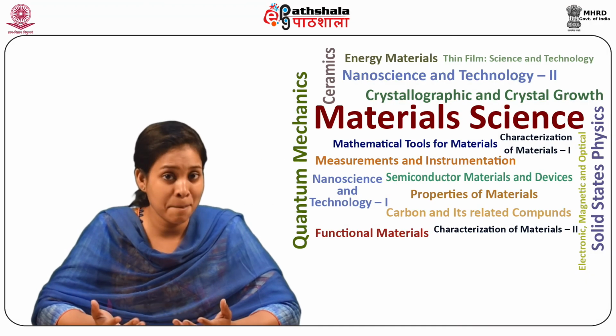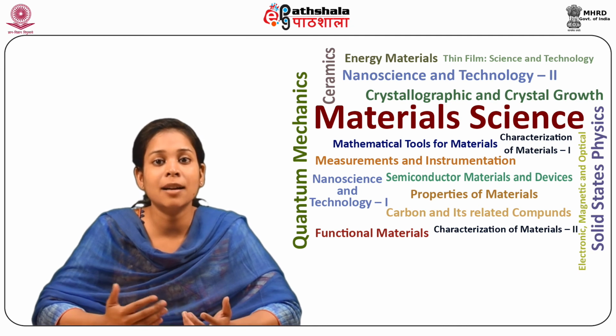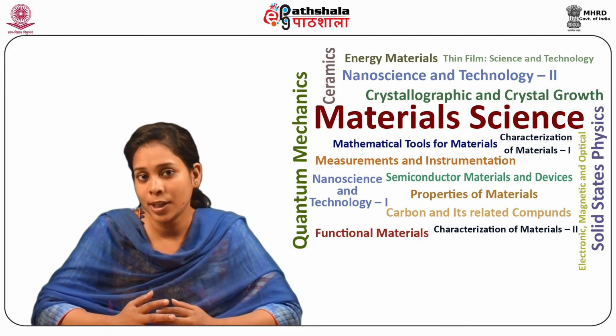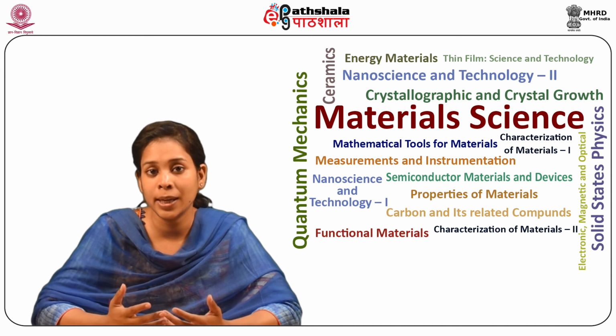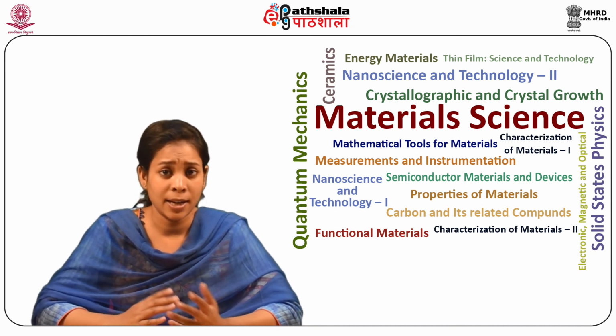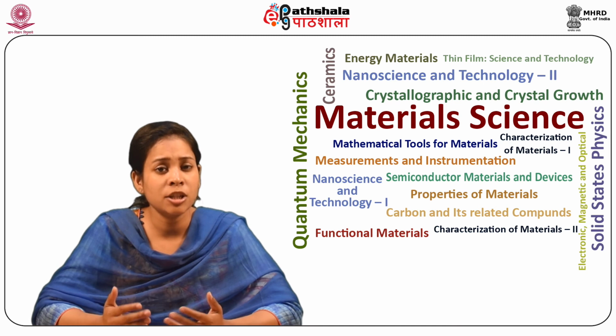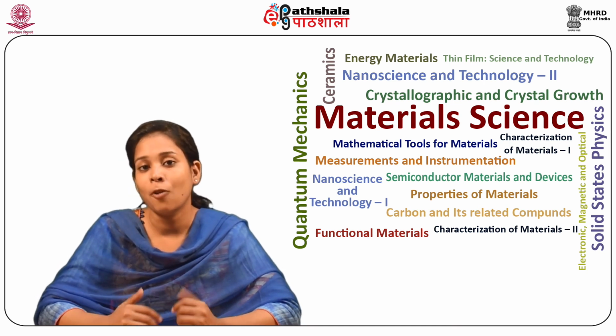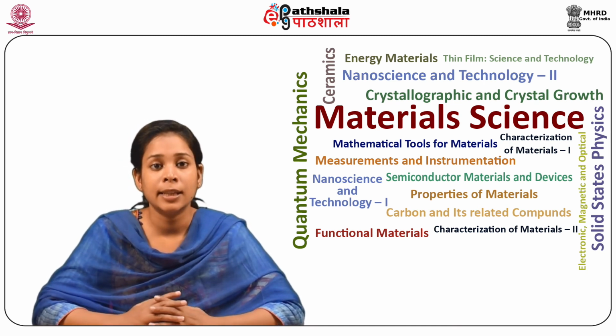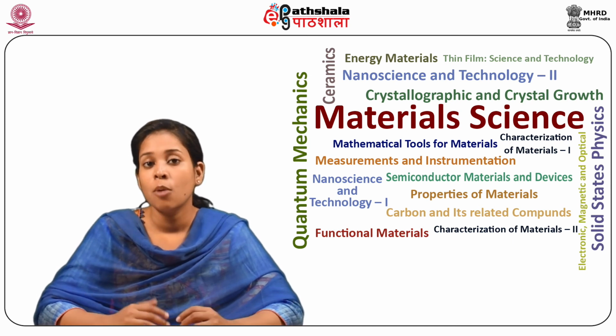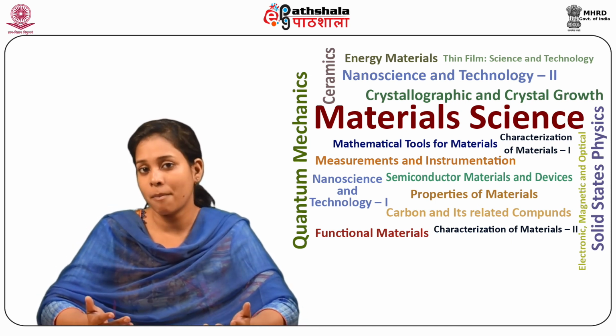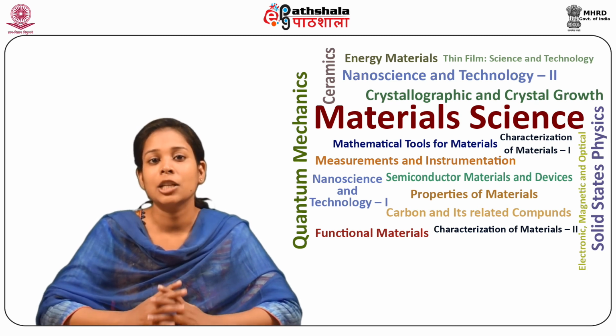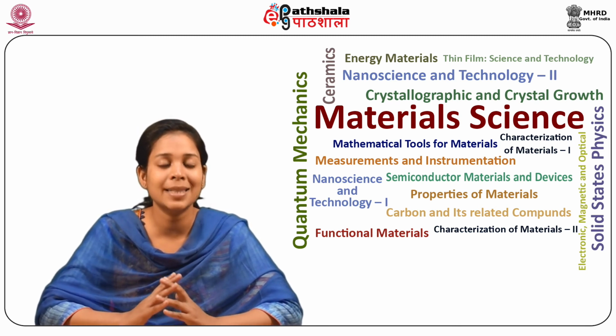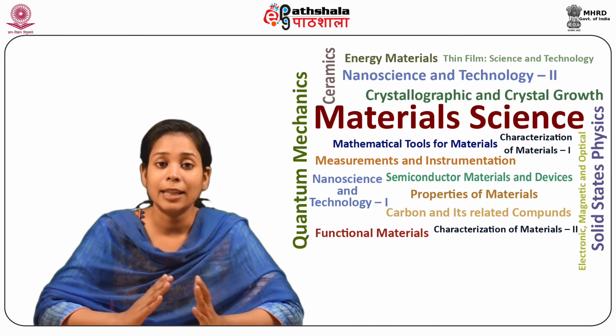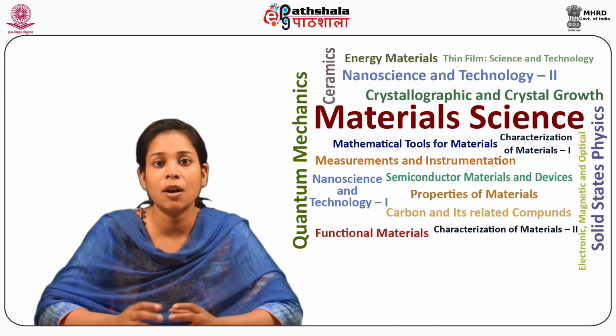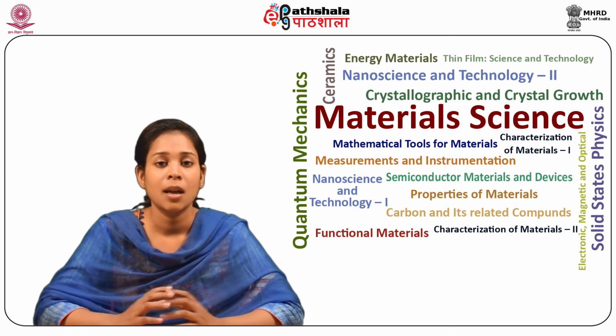As an example, in the case of silica glass, the structural units can be taken to be SiO4. In the liquid state, these units further link together to form larger units. In the case of polymers, most of which also form a glass on cooling, the structural unit may be segments of a chain, each segment containing a few carbon atoms.